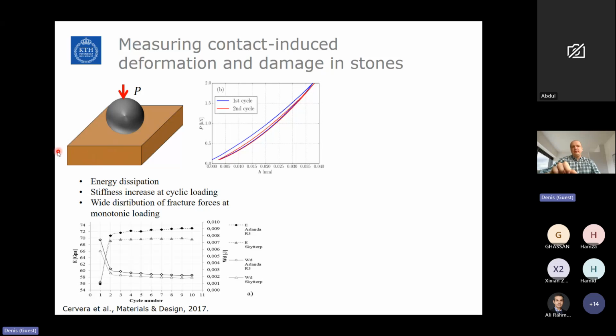We take a flat stone plate and indent a very stiff ball made of tungsten carbide into the material. And we've done two different types of experiments. We've done a cyclic contact experiment where we apply load over 10 cycles to the material, a relatively small load. And we measure applied load and stone deformation. So this is what you see here.